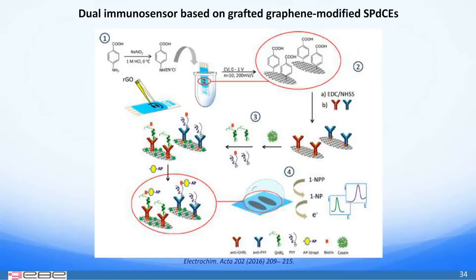As an example, I have selected a very attractive disposable immunosensing platform for the simultaneous determination of two obesity-related hormones, ghrelin and peptide YY. In this case, dual screen-printed carbon electrodes were modified with reduced graphene oxide, and after grafting of the diazonium salt of 4-aminobenzoic acid on this modified electrode surface, the corresponding capture antibody for its target hormone was covalently immobilized onto its working electrode using carbodiimide succinimide chemistry.